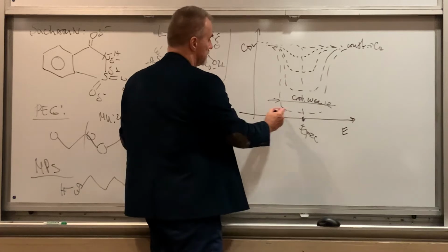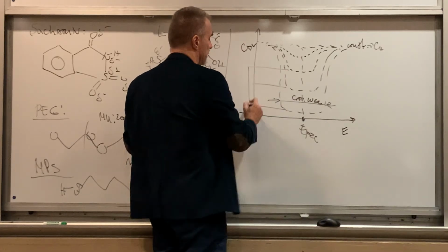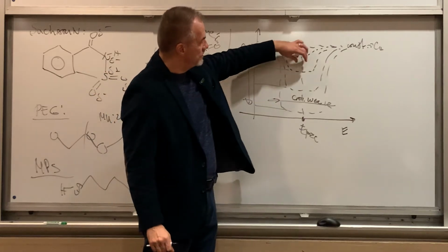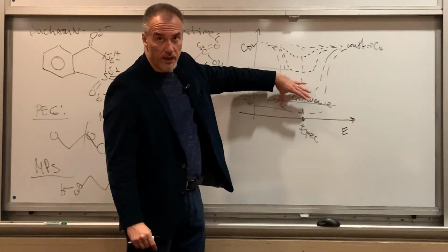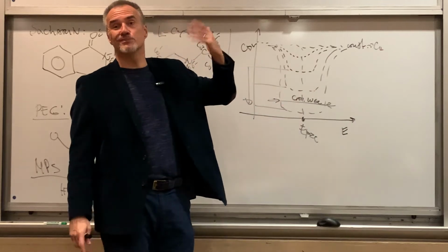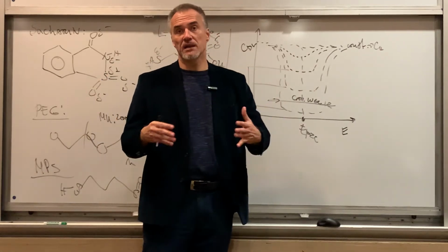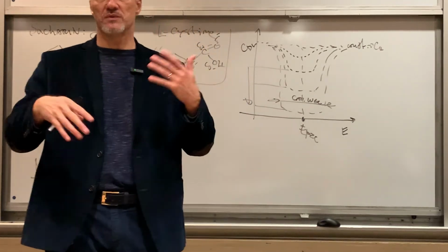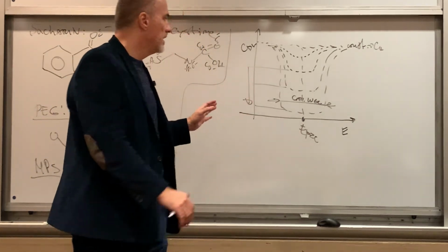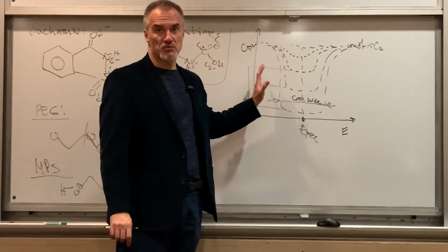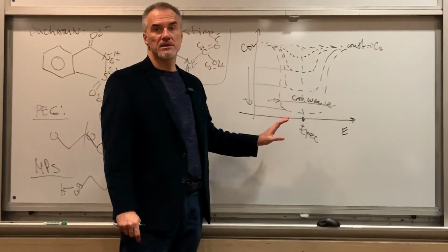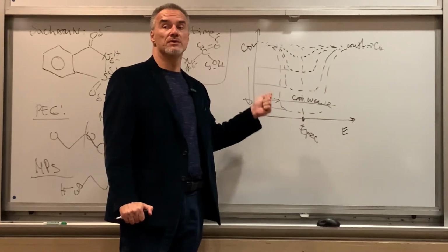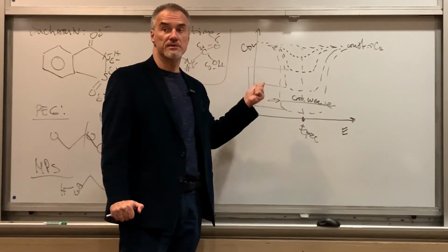This level of C minimum will be going this way with increasing concentration of the additive, but also it's going to be widening up, right? Now that's a textbook example. In reality, systems are very difficult to measure if you have hydrogen coevolution with this kind of measurement. So in reality, it doesn't look so pretty as I draw, but that's the signature that your additive actually is interacting with your electrode surface, meaning adsorbing.